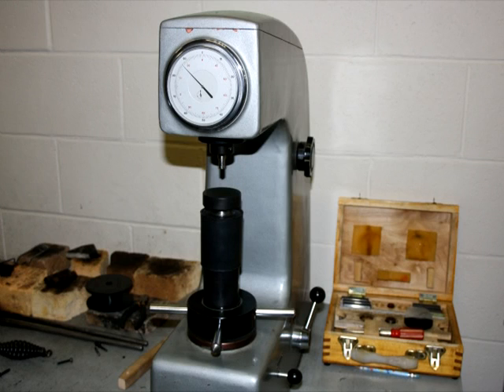100 kilogram load. So let's perform a Rockwell C hardness test on a V-block that was made with 4140 steel. It has been hardened, so I would fully expect it to be somewhere around 45 Rockwell C. Here we have a Rockwell hardness tester. This machine measures Rockwell C and Rockwell B scales. Now basically, the Rockwell hardness test consists of measuring the depth of penetration of a penetrator and deducing from the depth of penetration how hard the material is.